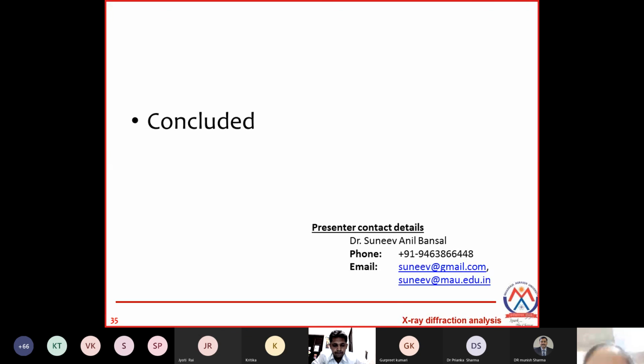Okay, the last question is, can we predict the structure of a crystal from XRD image, like tetragonal, cubic, or orthorhombic? Yes, very much possible. For example, if you are going for BCC and you are going for FCC, for all the planes where the face centered atom is present, calculate the distance for that. If that distance is present in the XRD peak, it means it is an FCC crystal. If that peak is absent, it means it is not an FCC crystal. It is very much possible.